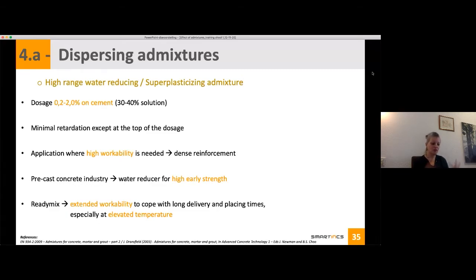There you can think of a structure with really dense reinforcement, where your concrete really needs to go in everywhere. For the precast industry, they are highly used as water reducer because then you have a high early strength. And for the ready mix, the positive impact is that you can have extended workability, so you can transport your concrete from your plant to a working place. This is also very positive if you work at elevated temperature.